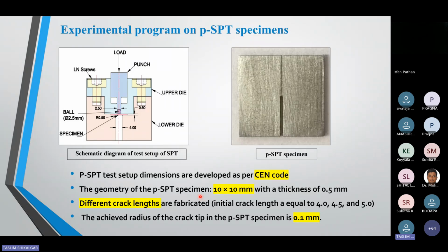So for this approach, you cannot study single crack length specimens. For that purpose, I fabricated different crack length specimens: crack lengths of 4 mm, 4.5 mm and 5 mm. And here I generated one ratio that is important. A is the initial crack length and W is the width of the specimens. So this becomes a non-dimensional number, a by W. Sometimes in fracture mechanics applications, people characterize these specimens using the a by W ratio. So here the a by W ratio becomes 0.4, 0.45 and 0.5. And in these specimens, I fabricated a crack with a radius of 0.1 mm. This is the minimum radius I achieved in the specimens with the help of wire EDM.